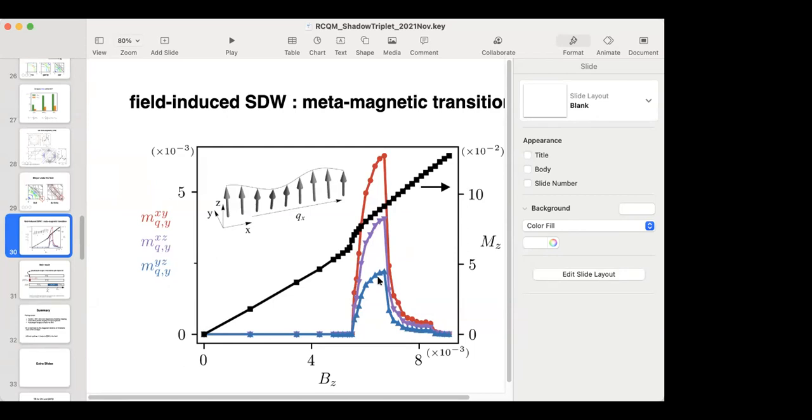I just wanted to return to Stephen's question. I do think that you would have a Van Vleck susceptibility coming from inter-orbital effects, or rather interband effects, and I suspect the Knight shift drop is due only to the intraband contribution to the susceptibility. But that was the comment.